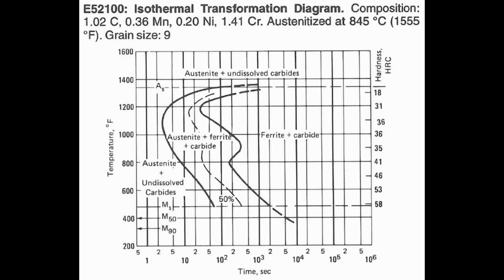This one is for 52100. One important element of a TTT diagram is what temperature they austenitize the steel at before creating the diagram. For this one, for 52100, it is 845 Celsius or 1555 Fahrenheit. So they heated it to that temperature and held, and then they would quench to different temperatures and hold and measure the transformation of the steel. Now, we are interested in the lower temperature range, so in this case, something like 500 to 600 degrees Fahrenheit or so.